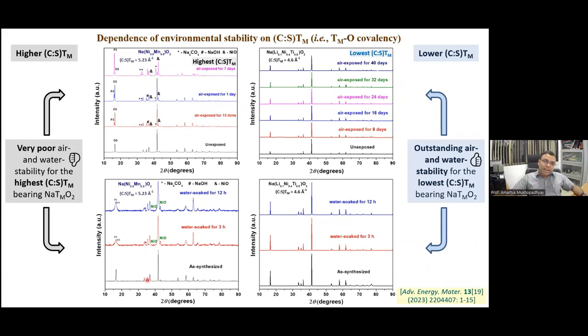on the left hand side, I have the highest charge to size bearing transition metal oxide, which we believe to be highly unstable when exposed to air and water. And on the right hand side, I have the lowest charge to size ratio bearing material, which we believe to be air water stable. And that is exactly what we see when we expose the materials to air for, say, 7 days or just within a few minutes.